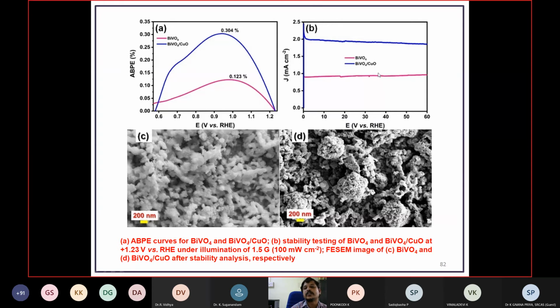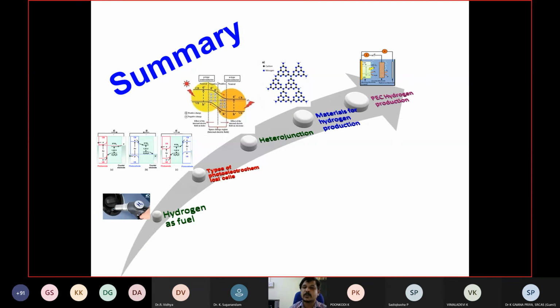Then the stability also we have proved with respect to time. Finally, the stability of the material also we have checked. After the hydrogen production, the properties don't change, the morphology doesn't change. So with this we have concluded this material is a promising one. Based on the result, we are developing several heterojunctions in our laboratory.